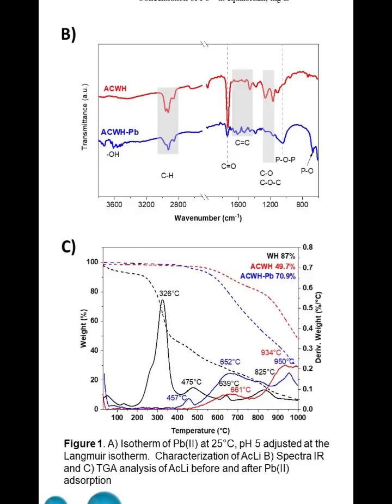Combined with the adsorption isotherm results, Figure 1a, which revealed a maximum adsorption capacity of 273.26 milligrams g^-1 and a predominant fit to the Langmuir model, Table 2, these findings suggest that Pb2+ removal is mainly driven by electrostatic interactions between the negatively charged carbon surface at pH 5, pHPZC 3.22, and Pb2+ ions, with chemisorption as a dominant mechanism.